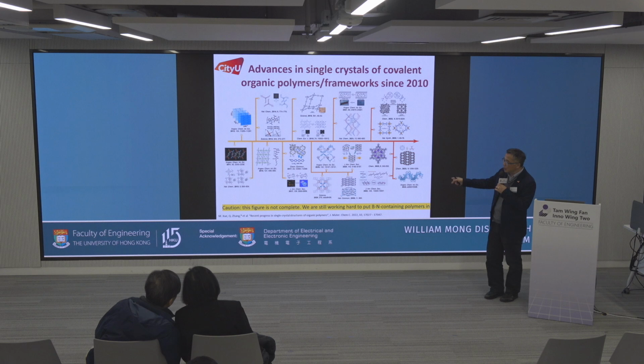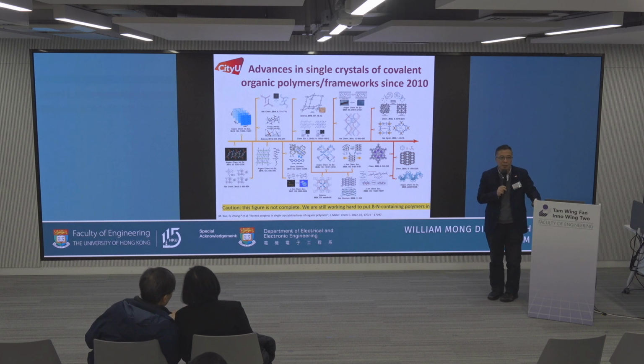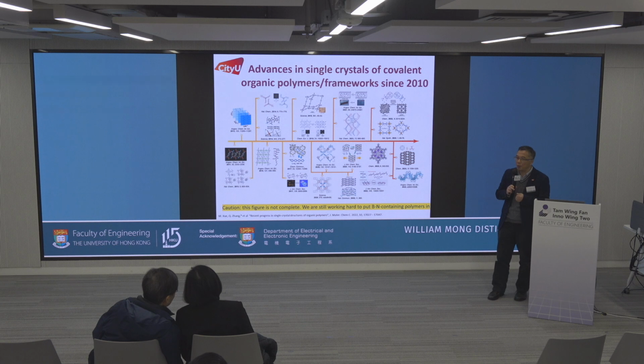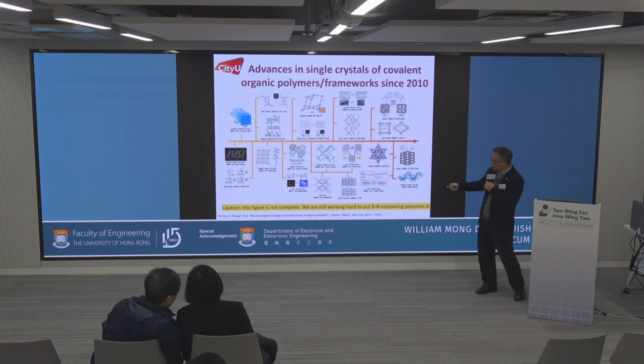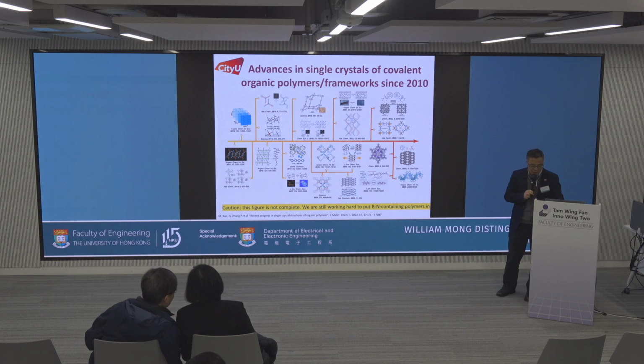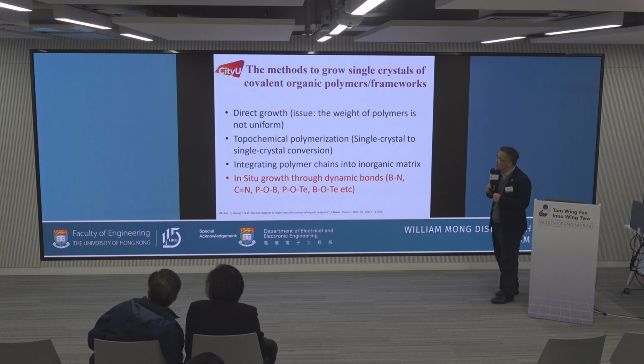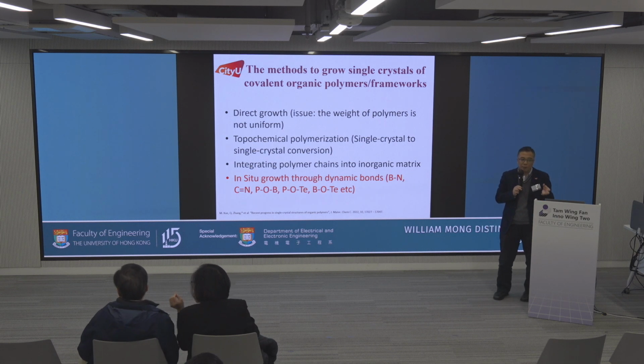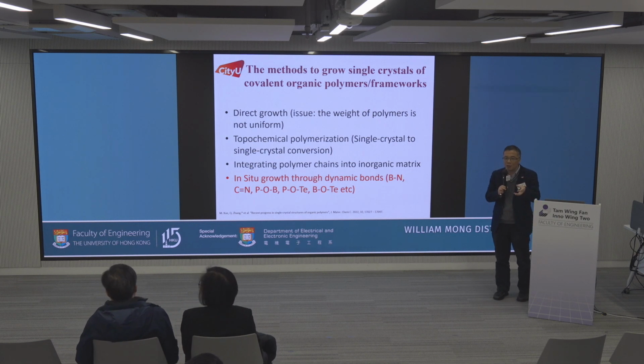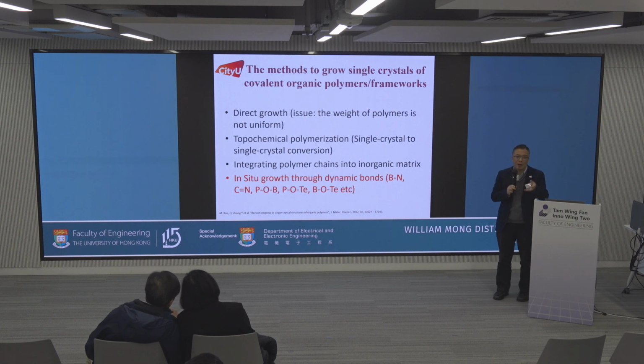So my group gave a summary of the recent years. You can see that starting from 2010, each year there are single crystals of polymers reported in the literature. My group summarized these single crystals, and we know there are four ways to grow them. The first way is direct growth. What do we mean by direct growth? We synthesize the polymer first, dissolve it in an organic solvent, and then evaporate to grow the single crystal.